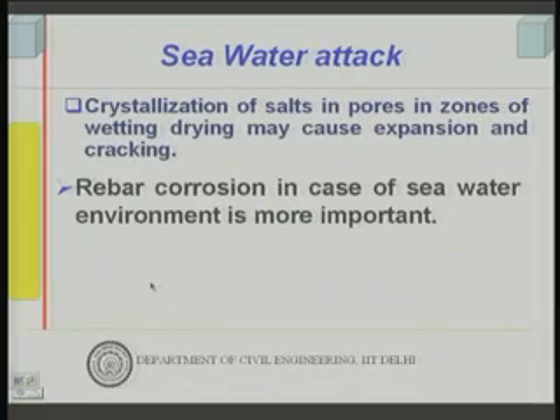Now, leaching causes problems because more seawater can penetrate, and therefore it is a kind of nonlinear effect. Leaching, further seawater penetrates, more leaching, and so on. Where there is wetting and drying, in the zone between the highest water level and the lowest tidal water level in the sea, crystallization of salts can take place in the pores, because there has been sufficient leaching and a lot of pores. Some of those salts will get inside the pores and the water will evaporate, and crystallization of salt can exert pressure onto the concrete structure. So, this may cause expansion and therefore cracking. This happens in the zone where wetting and drying takes place, and not of course in a completely submerged situation.